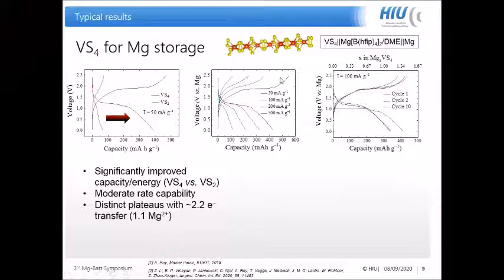So the overcharge showing in the charge-discharge plateau, I was thinking, maybe comes from some side reaction of the cathode. For example, when we have the breakdown of the sulfur-sulfur bonds, this might not be 100% reversible, so that we are losing some capacity. Maybe there will also be a small amount of magnesium sulfide formation, which is just detached from the structure. And as you mentioned, Max, in the case of lithium-sulfur or magnesium-sulfur, we have this overcharge. So it might be similar here. Of course, it's probably a different mechanism.